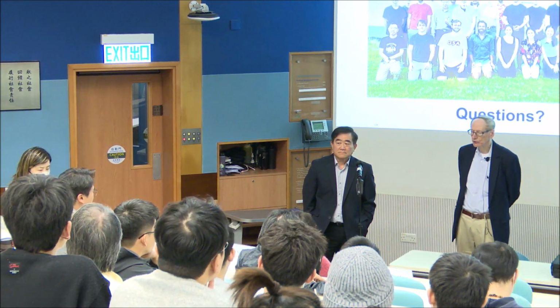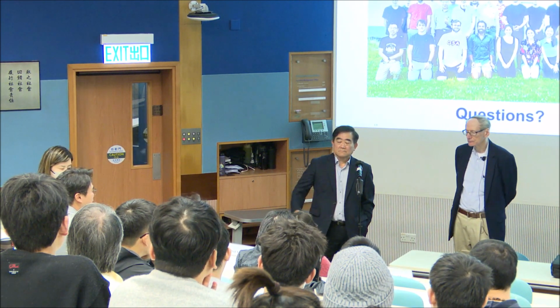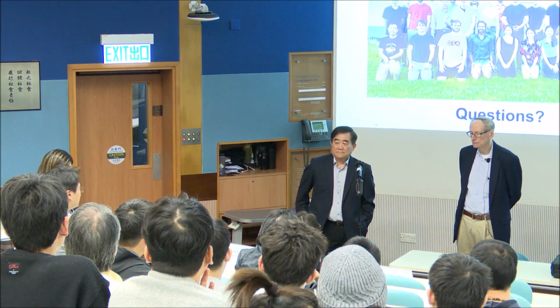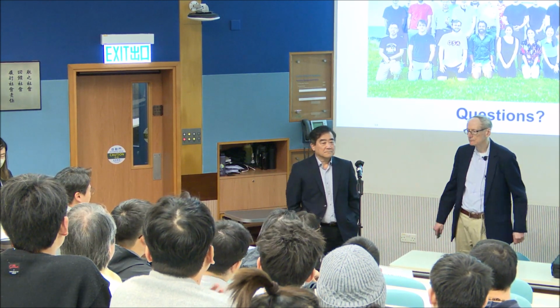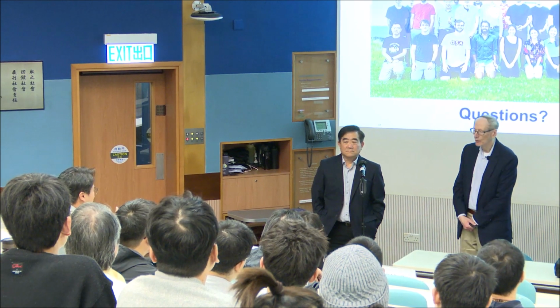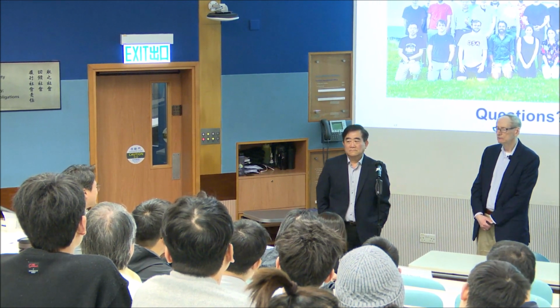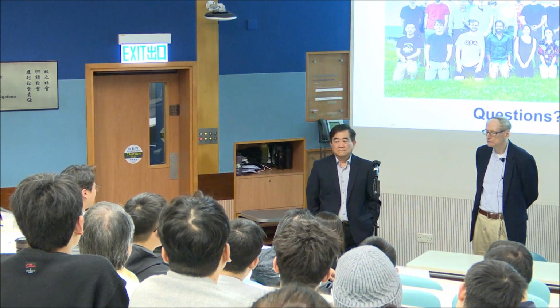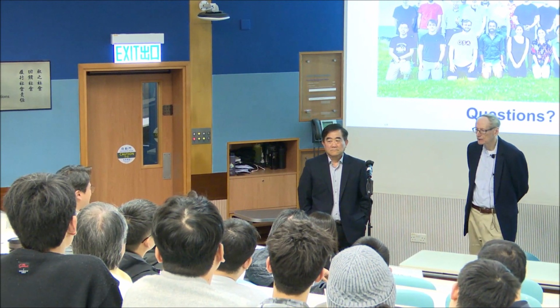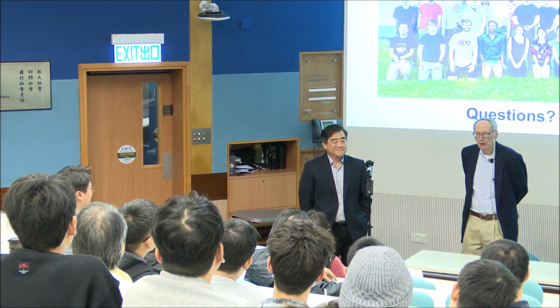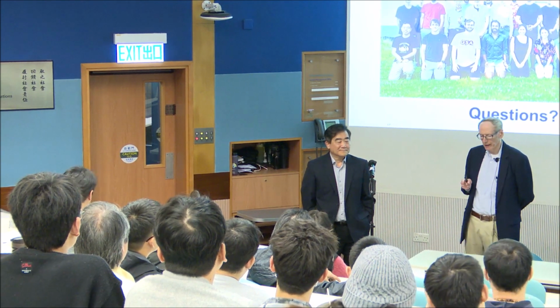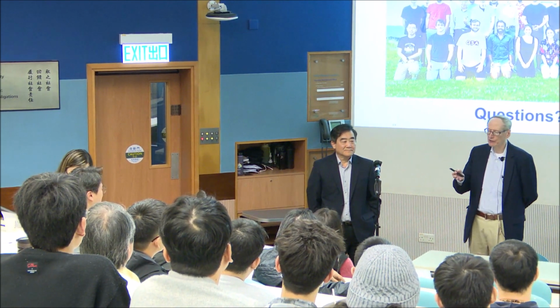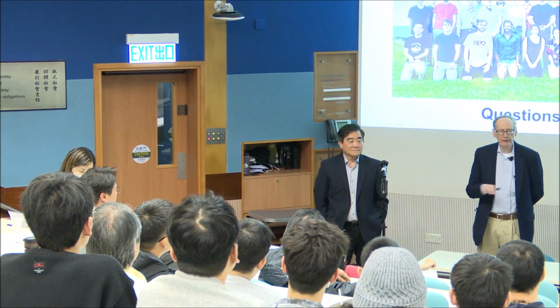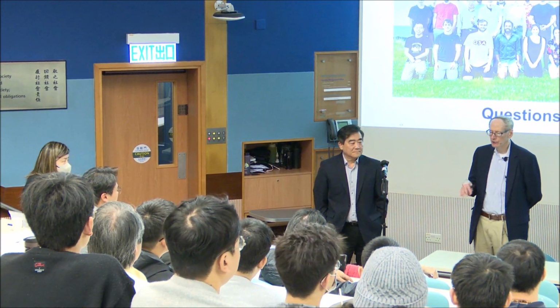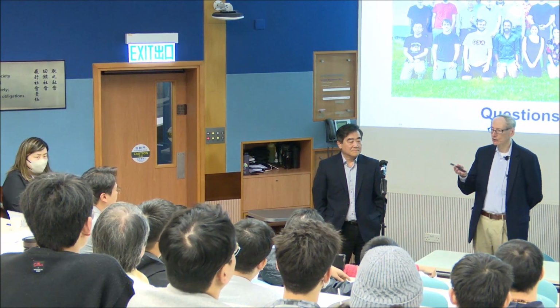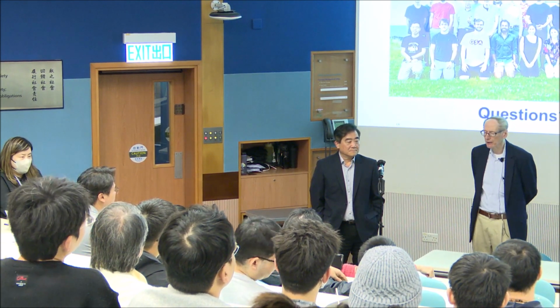Maybe I have a follow-up. Sure. You have shown a very wonderful mobility of your metal oxide on your SAND dielectric. But you also have a silicon dioxide layer as a protective layer between them. So is there any reason you have a higher mobility on top of that SAND? In that particular experiment, we were using PLD, pulsed laser deposition, and it turns out that a very thin layer of silicon dioxide protects the SAND from the laser damage. But when we do it other ways, we don't need that layer.